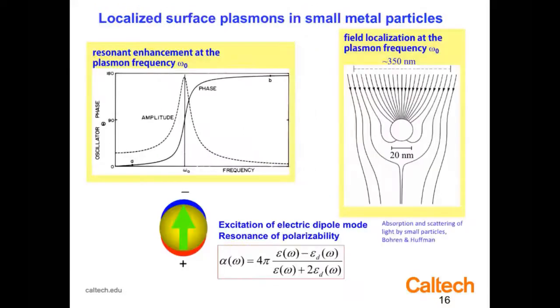So that resonant absorption is coming from the polarizability, the polarization response of the metal particle, just like an atom is polarized. The bound electrons in an atom are polarized in an electric field and generate a resonant susceptibility response. So the electrons in a small metal particle exhibit a resonant susceptibility. You have a resonant rise in the real part of the absorption or scattering, and you also have an imaginary part, which gives rise to a phase shift. And that phase shift will turn out to be very important.